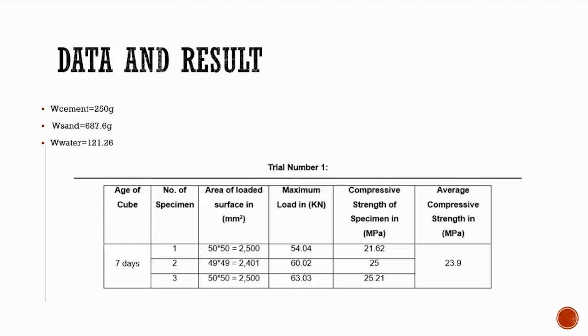Specimen number 2 has a loaded surface area of 49 by 49, which equals 2,401. Maximum load is 60.02. Compressive strength of the specimen is 25. In number 3, the area of load is 50 by 50, which equals 2,500. Maximum load is 63.03. Compressive strength is 25.21. The average of all 3 specimens is 23.9.